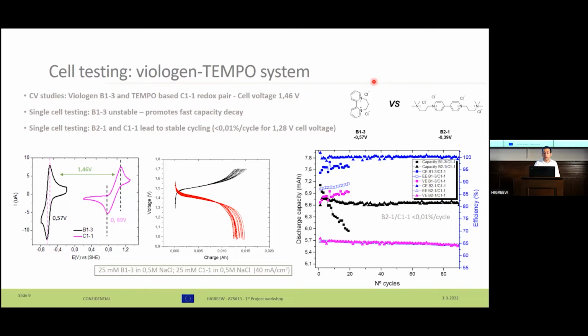To confirm this, we did evaluation using this compound, which the stability is well confirmed in the literature, this 4,4-bipyridinium salt, in which in this graph we can clearly observe how the stability of this compound, just focus on the black traces, is that the B21 compound coupled with our tempo derivative is showing a really low capacity decay, less than 0.01% per cycle, while in the case of using this 2,2-bipyridinium salt, the capacity decay is dramatic. In this sense, with these redox couples, we have a cell voltage of around 1.3 volts.